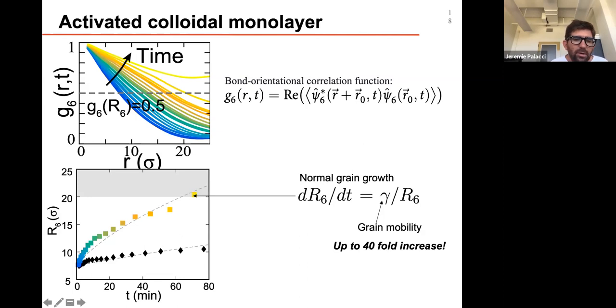Now, in order to quantify those curves, we looked into grain growth. For thermal systems which are aging, there's a large body of work arguing what power law you should use during grain growth. We decided to go for the simplest description, normal grain growth, which is curvature driven. So we end up with dr/dt = gamma/r, where gamma is the grain mobility. We could qualitatively describe our experiment with this normal grain growth, which gives R6 going like the square root of time.